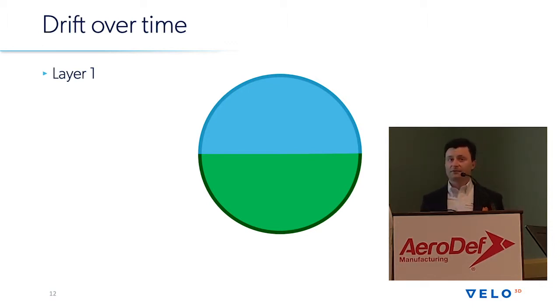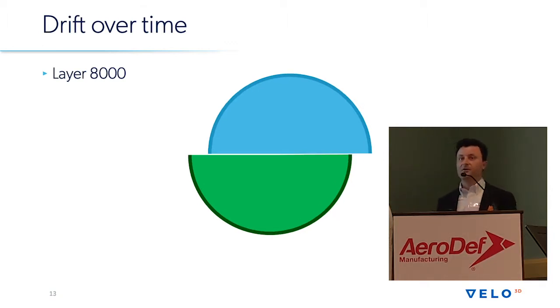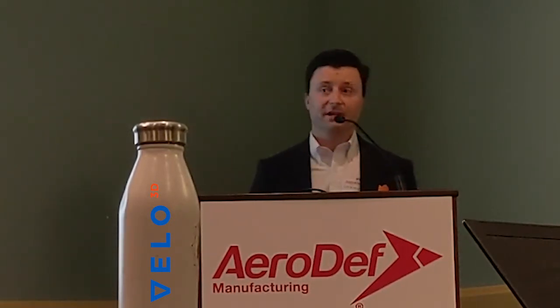This is well and good if your laser is aligned on layer 1, but when you get to layer 8,000, things move. And you can see this a lot of times in the overlay because the overlay will shift as a function of Z. So you'll actually start to see more overlay shift as you get higher in the part. And the question then is the part good? You didn't have a pause in the build. You didn't violate some of the build restrictions that you might have around building a part production. But the question remains, what's inside the part, right? Do I have an area in the part where I haven't fused the metal? On this overlay, is that okay for a dynamic mechanical test for high cycle and low cycle fatigue? It can be questionable at that point.